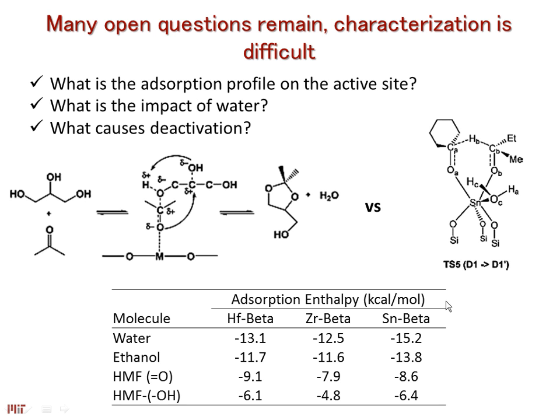And we have a lot of questions remaining of what is happening over here. What is the impact of water? What are the adsorption profiles on the active site? What is causing this deactivation? And we know it's not coke formation because our MPV step, or transfer hydrogenation step, remains active. So we have a lot of potential questions of what is happening over here, what is the mechanism, but there's limited ways in which we can really probe the structure, we can probe the active site.